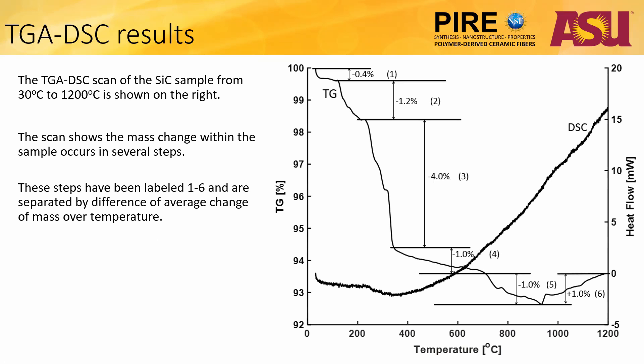There is an initial mass loss of 0.4% during the temperature increase from 30 to 120 degrees Celsius, then a greater mass loss of 1.2% between 120 and 220 degrees, followed by the largest mass drop of 4% between 220 and 350 degrees. Then, during a much longer period between 350 and 715 degrees, there is only a 1% mass decrease. Following that is a similar mass decrease of 1.0% between 715 and 935 degrees, before a mass increase of 1% from 935 degrees to 1200 degrees.